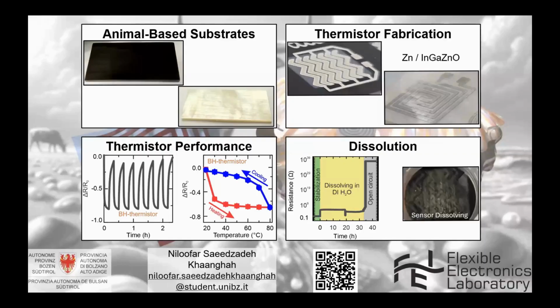In conclusion, for the first time, we used animal-based substrate to fabricate thermistors on top. What we did was deposit 2 layers of materials, zinc and indium gallium zinc oxide semiconductor, and fabricated the thermistors. We did the characterization, as you see. The sensors showed quite stable and reliable signals during multiple tests and high hysteresis. Also, the dissolution test was successful on these sensors.